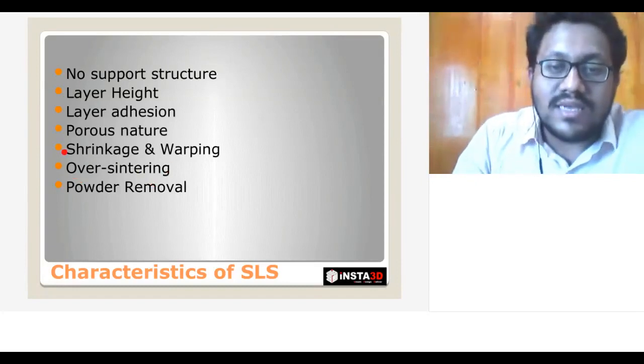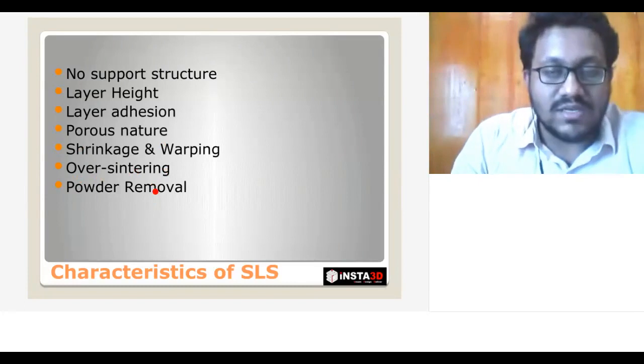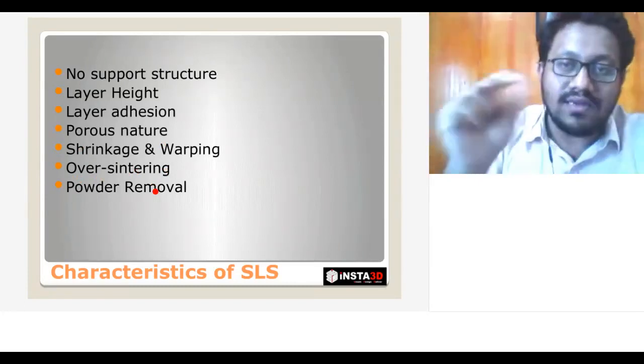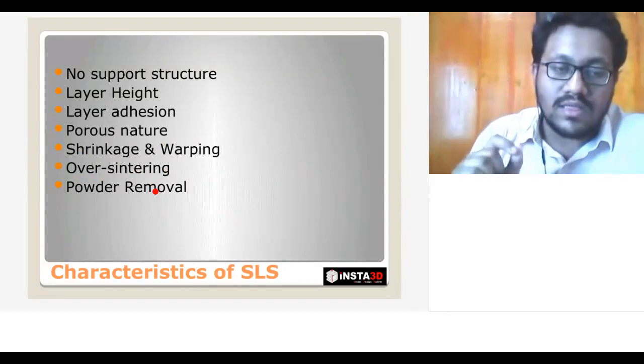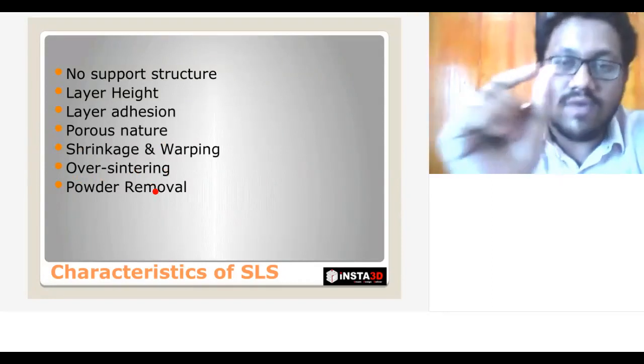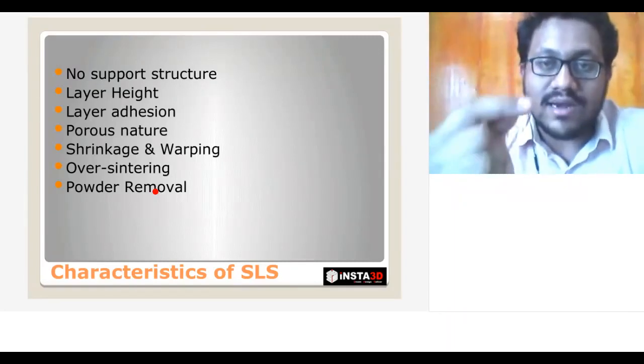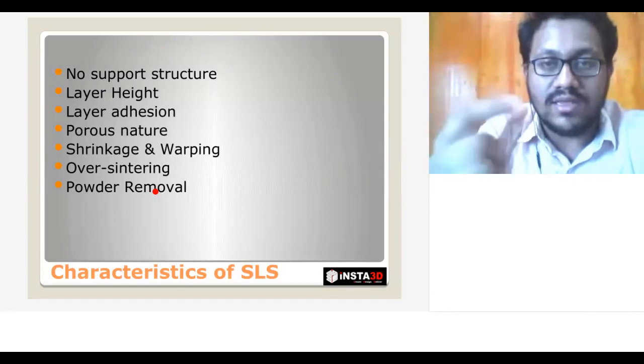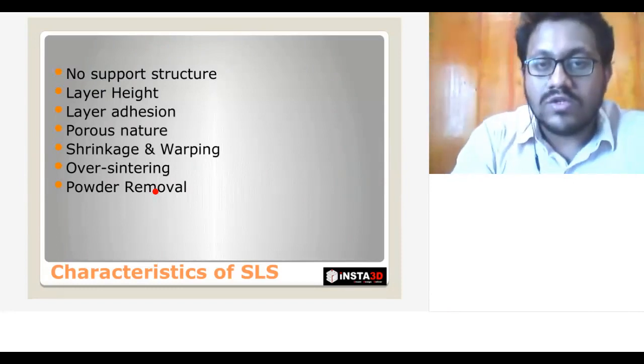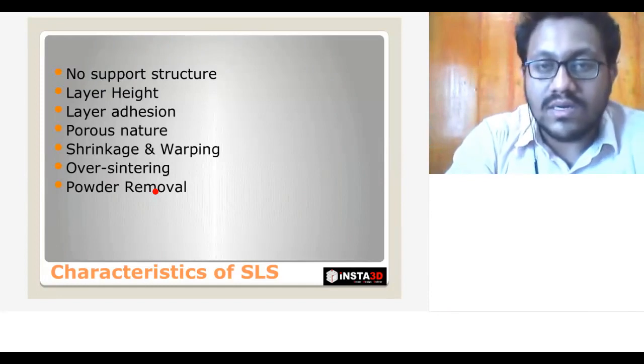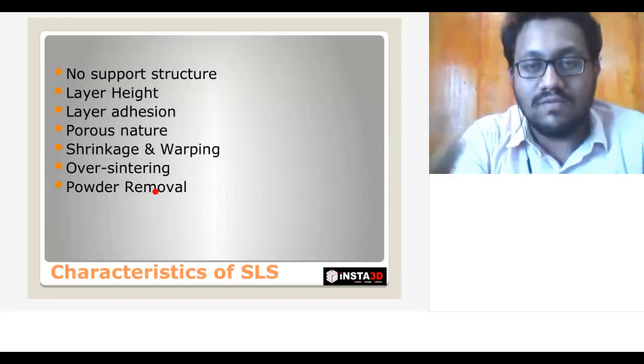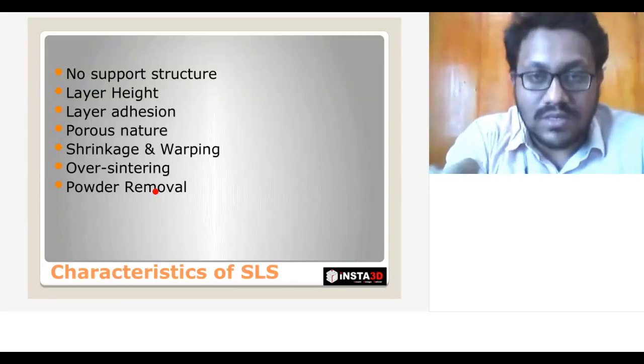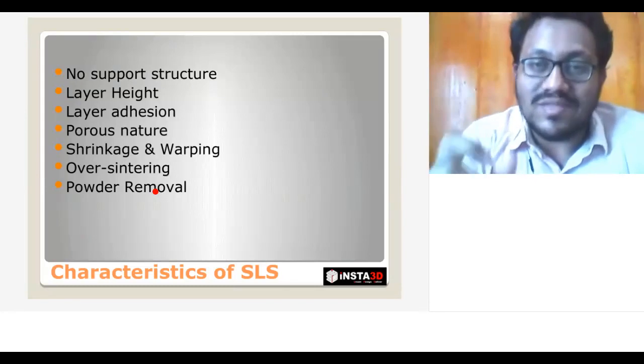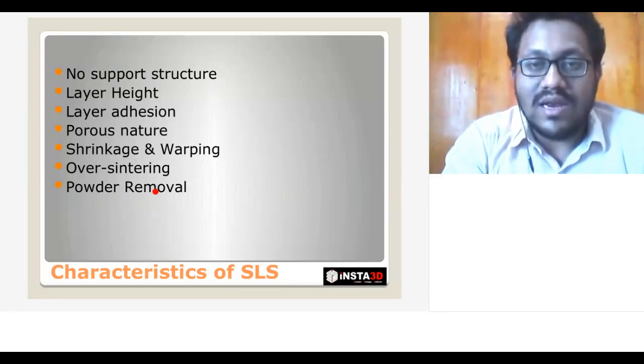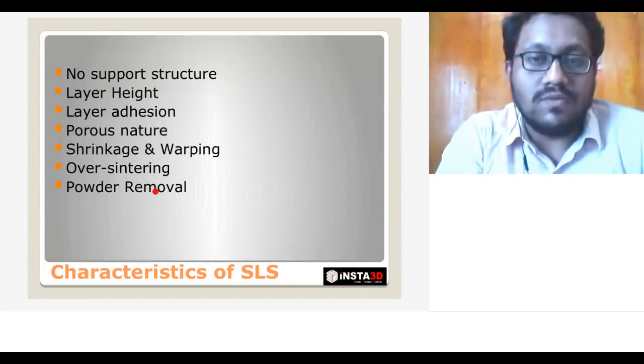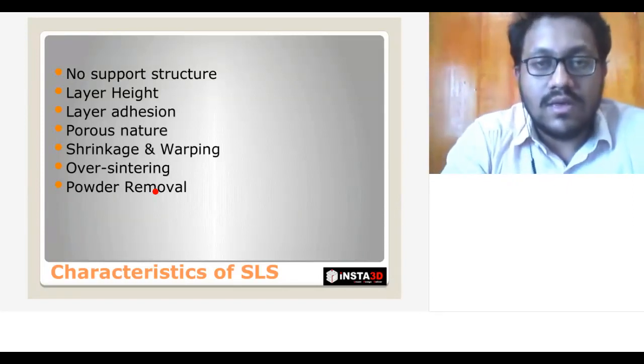And there is a case of over-sintering which is happening in SLS technology. This over-sintering is like high heating of raw material. So once the laser is focused onto a raw material, if we have say 1 mm wall thickness and there is a 1 mm dia hole in the cross section of 1 mm, the 1 mm hole gets over sintered and there will be no hole visible when we get the 3D printed output. It is because of over sintering. So we need to increase the wall thickness, or we need to control the laser parameters accordingly so that you can get a full good 3D printed component out of the SLS 3D printer.